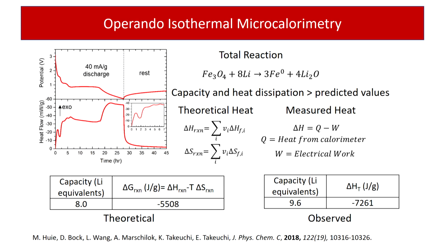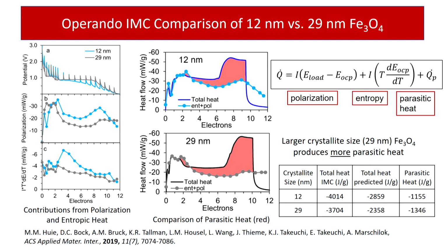And what we find are two interesting things. We know the theoretical reaction should generate 8 electron transfers. We can calculate the amount of heat we should produce, and in fact, we get more than 9 electron transfers, and we get more heat than should be predicted. And if we look at 2 different crystal sizes, 12 nanometer and 29 nanometer, to be honest, unexpectedly, we saw that the parasitic heat is greater for the 29 nanometer.